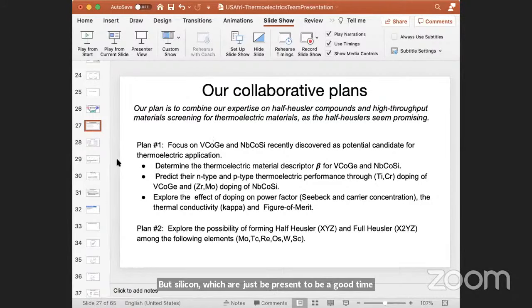So we try to look at the thermoelectric material descriptor, which is beta, for the two compounds, and also try to predict the N-type and P-type thermoelectric performance through doping of these two half-Heusler compounds. And we want to see if by doping this material, we can possibly increase the power factor and reduce the lattice thermal conductivity, and in the process increase the figure of merit. So our second plan is to use the screening technique of Elif's group to screen some elements, to see if it is possible for us to have good thermoelectrics from half-Heusler alloy and full-Heusler alloy from this series of elements. Next slide.